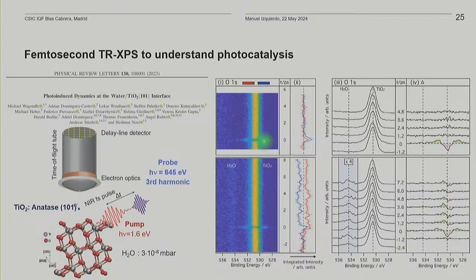So they did the first experiment where basically they measured the pristine titania, prepared under very special conditions. They did the annealing in oxygen atmosphere to make sure that there were no vacancies or interstitials in the system, so to get the surface as stoichiometric as possible. And then when you do a time resolved experiment, and you take a spectrum in this area, this is red, and this other area, this would be blue. What you see is that only around time zero there is this excitation that we call sidebands, and this is related to the interaction of the laser with the electrons getting away from the sample.